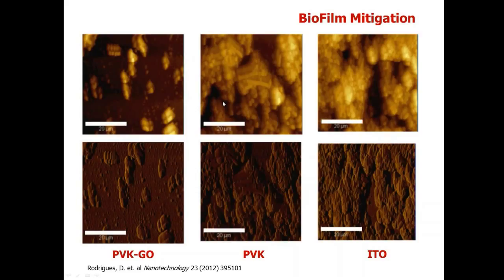On the other hand, the PVK-GO shows very little biofilm formation after a few days because of the presence of the PVK and graphene oxide.